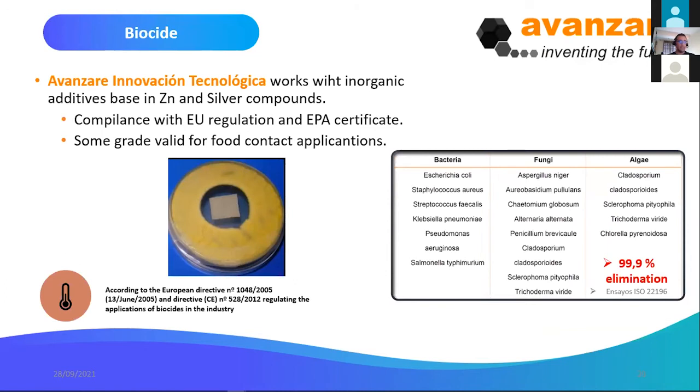Finally, I would like to say some words about those biocide solutions. At Avanzare, in this case, we are working with inorganic additives based on zinc and silver compounds. These products are compliant with European regulation and EPA certificate, and some grades are valid for food contact applications. Our biocides are valid for a large spectrum of different microorganisms like bacteria, fungi, algae, and it's possible to get an elimination higher than 99.9%.